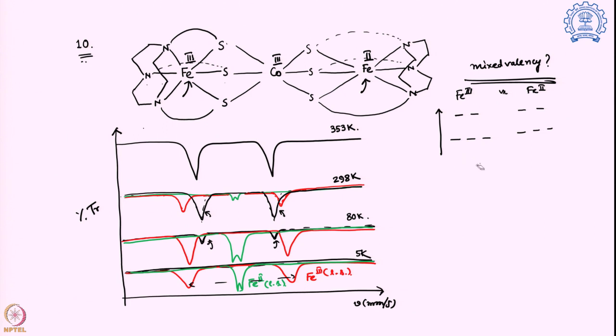Over here we can say this is the EG level and this is the T2G level. Iron 3 means a D5 system, iron 2 means a D6 system. So over here we have 1, 2, 3, 4, 5, because these are low spin systems. Why low spin? We will come to that a little bit later. It is because of the presence of the sulfides, which are coordinated with this cobalt 3 plus system, which is very strongly charged, and the interaction is such that this becomes a low spin system. The same thing happens over here, a D6 low spin system.